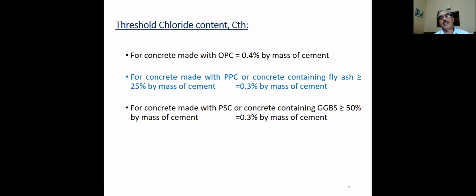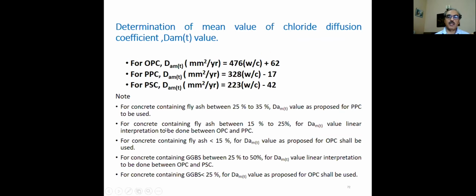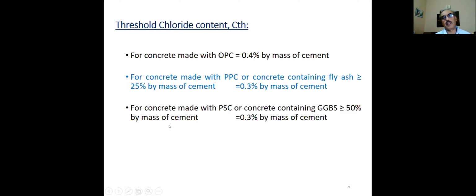Threshold chloride content: earlier, generally in ACI also, it was taken as 0.4 by mass percentage of cement. But research done, specifically data given by Professor Radhakrishnan Pillai from IIT Madras, found that in case of PPC and PSC, though the resistance to chloride ion is more, the threshold value is less than OPC.